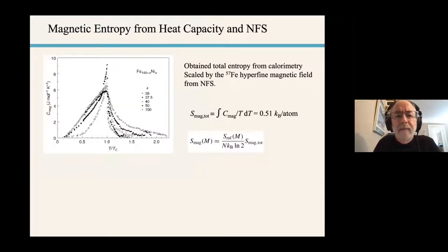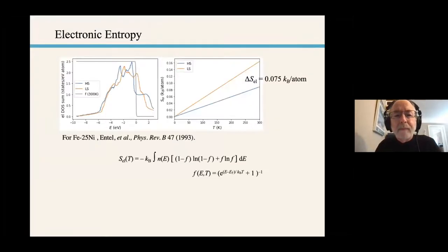We did find, fortunately, some heat capacity data for iron-nickel alloys and the magnetic transition in that, that allows us to calibrate the change in the magnetic entropy as we're seeing it in the hyperfine patterns. And so we have an approximation to how the magnetic entropy is changing with pressure. Now, we also found in the literature some electronic densities of states where we look near the Fermi level to get the electronic entropy. Unfortunately, this is the wrong composition. It's an old paper. I think we can do much better ourselves. We just haven't done it yet.